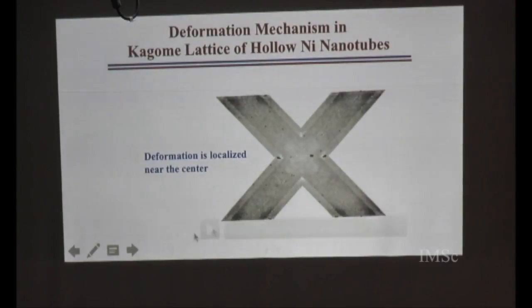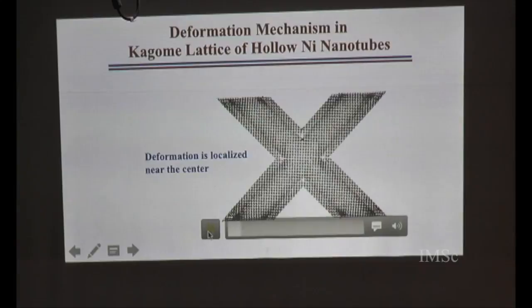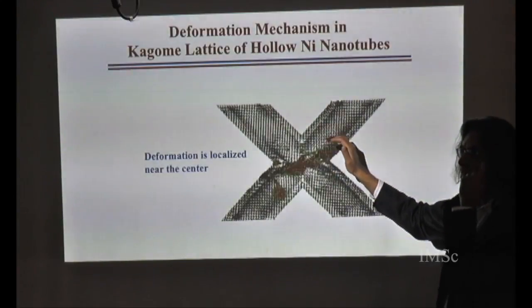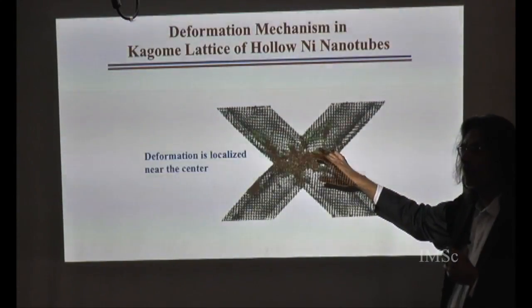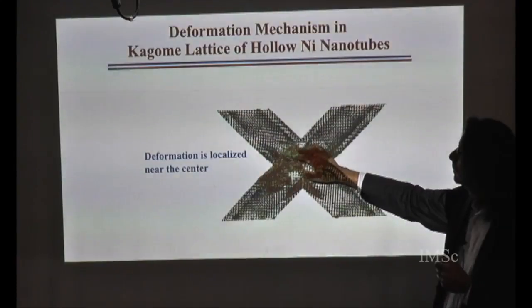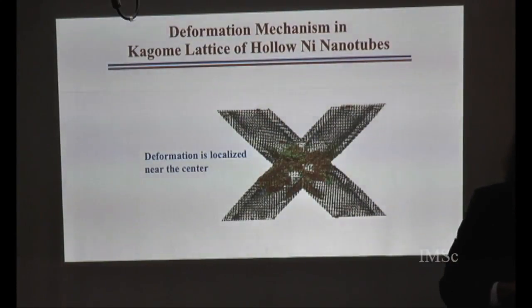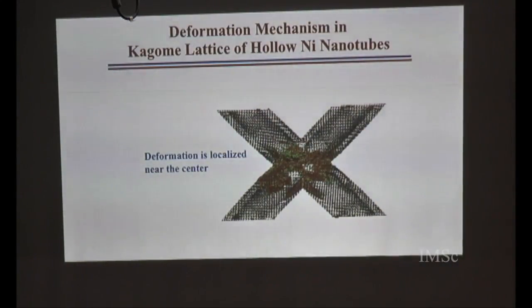Okay, so coming back to this is in the hollow case, and here, as you can see, the nucleations really start from here and then they travel in the system. So that's the difference between the nature of damage in the two systems. In this case, dislocations are localized near the center of the system.